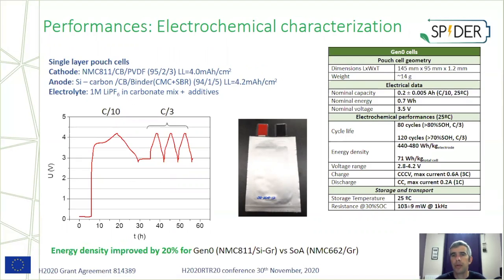We obtain a very good reproducibility regarding the nominal capacity with 0.2 Ah. The cycle life is still limited with 120 cycles at 70% of state of health, but the energy density is quite good, 480 Wh per kilogram of electrodes. If you compare with state of the art made of NMC 622 and graphite, we did this comparison in a benchmark study, the energy density is improved by 20%.